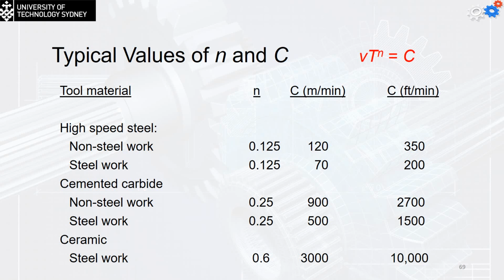For the ceramic, you can have n equal to 0.6, but the C value will go up to 3,000. Cemented carbide is 900 by 500. So you'll say, okay, I'm going to use ceramic for all the work. That's wrong, because ceramic cannot take a high depth of cut. That means you are going to increase the number of passes. So still, cemented carbide is the best option you can have during the cutting operation.